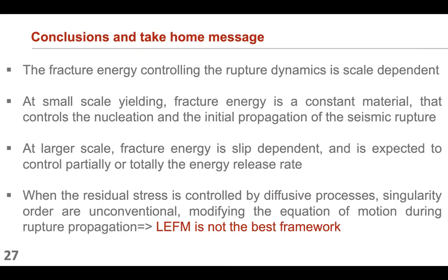And so finally, when the residual stress is controlled by diffusive processes, so it's never reaching a constant value far from the rupture tip, the singularity order becomes unconventional, and this modifies the equation of motion during rupture propagation. And in this framework, in fact, LEFM cannot be used simply to analyze the dynamics of the rupture front.